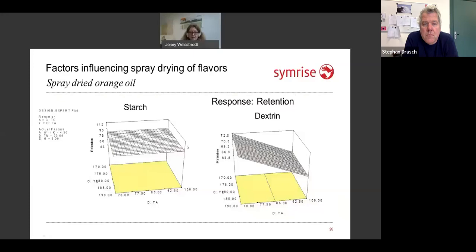Let's have a look at the starch. It's a very nice emulsifying property material. It makes perfect emulsions with our spray dryer, with orange oil, and whatever I do with the temperatures, inlet air temperature, outlet air temperature, we will have almost the same result. It just depends more on the homogenization process.